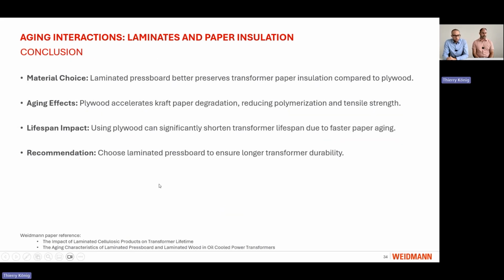So the conclusion out of this investigation is that laminated pressboard better prevents the aging effect on the transformer paper insulation compared to laminated wood. So plywood has an accelerating effect on the paper degradation. Then for the lifespan, we have an impact when we use plywood instead of pressboard material. Therefore, the recommendation is to use laminated pressboard to have a longer lifetime of the transformer.